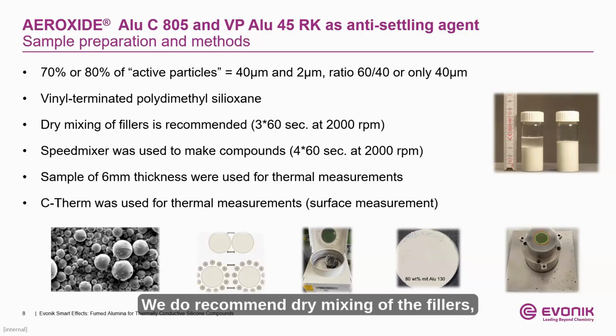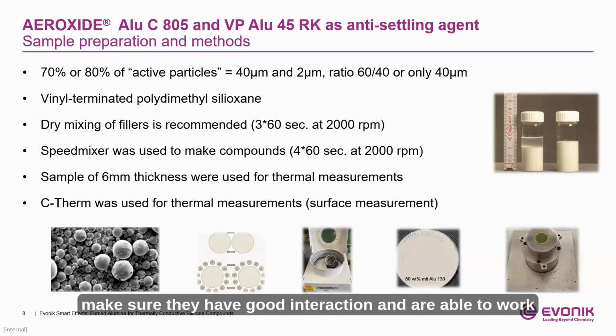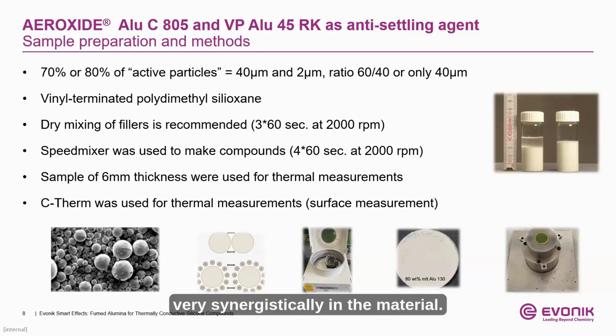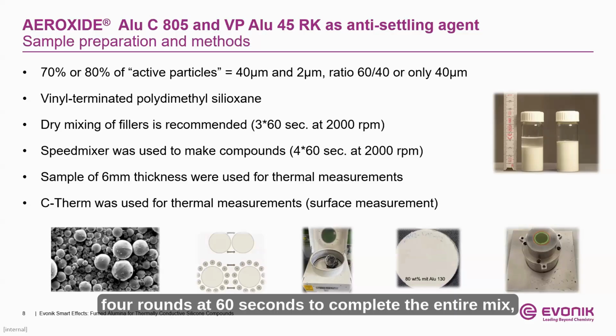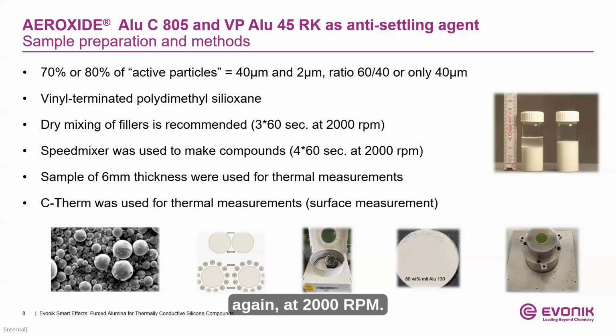We do recommend dry mixing of the fillers, basically meaning to mix the spherical alumina and the fumed alumina together by itself. This was done here in a speed mixer, 3 rounds at 60 seconds at 2000 RPM, just to homogenize the fillers themselves and make sure they have good interaction and are able to work very synergistically in the material. To make the compound itself, the fully formulated compounds, again, was done in a speed mixer, 4 rounds at 60 seconds to complete the entire mix, again at 2000 RPM.